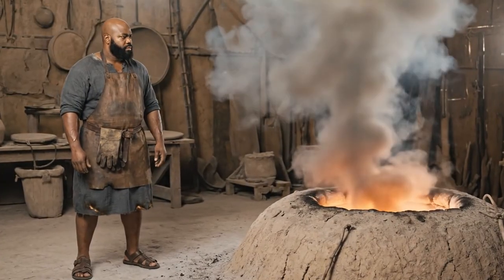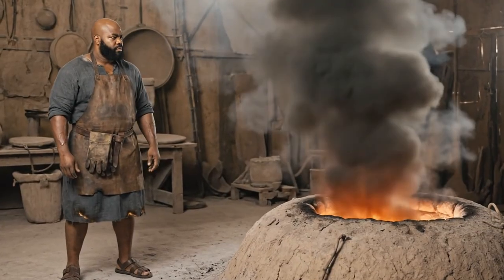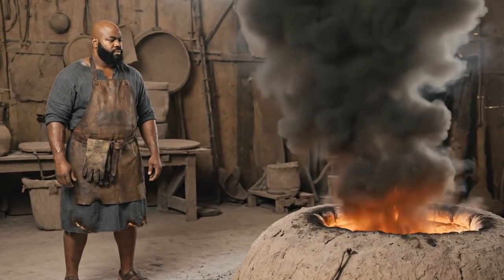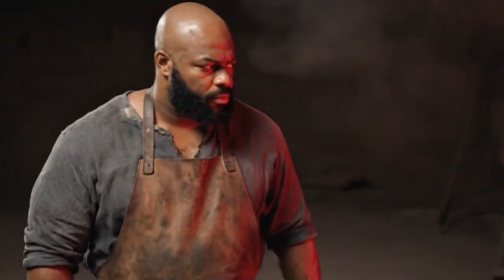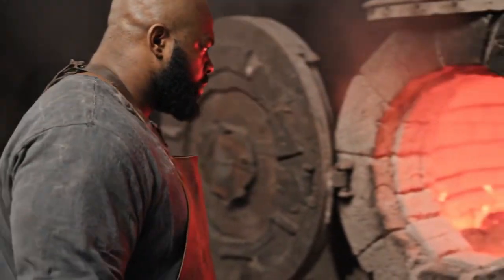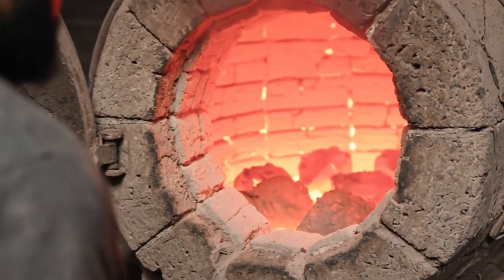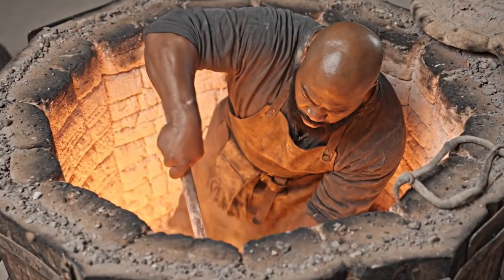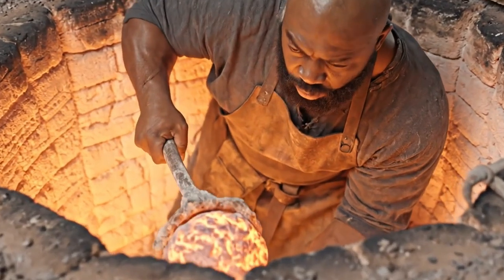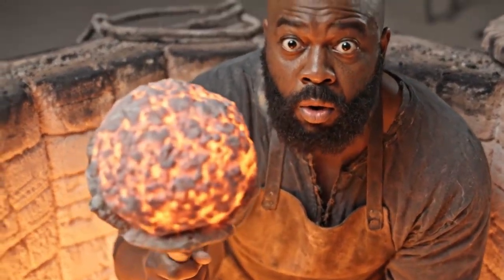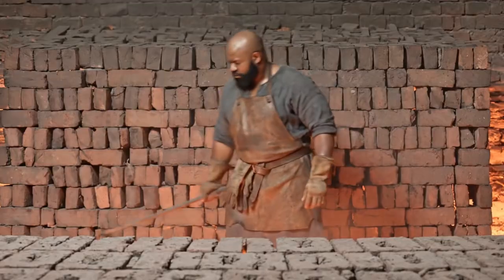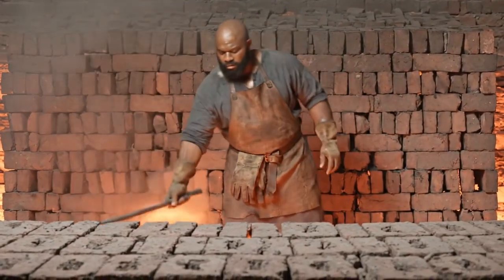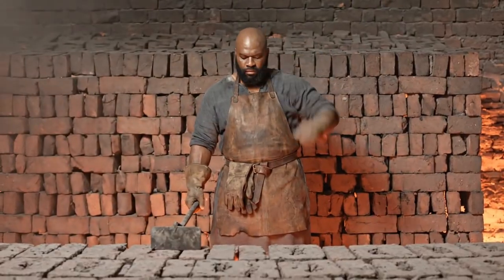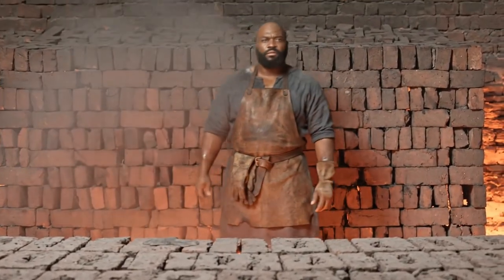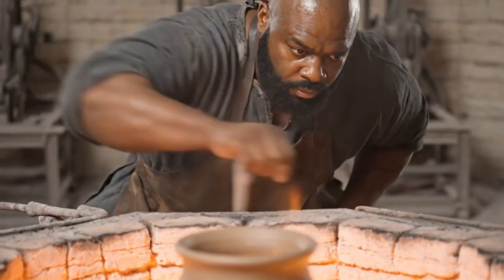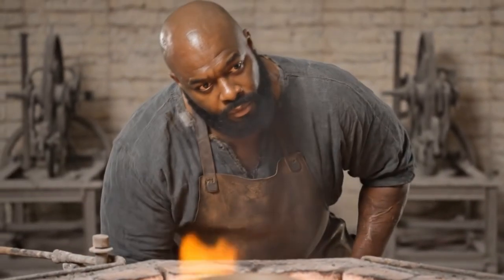First, the water smoking phase, where residual moisture turns to steam. Then, the black smoke phase, as organic matter in the clay and straw burns away. Then, the oxidizing phase, where the kiln reaches cherry red heat and the clay particles begin to vitrify, fusing together at the molecular level into a substance harder than any stone the Babylonians can quarry in their region. And finally, the peak temperature, somewhere around 1,000 degrees Celsius, held for several hours to ensure complete firing throughout every brick in the load.